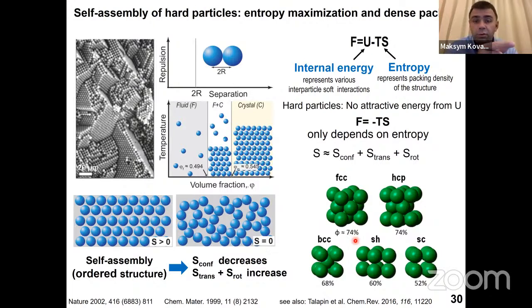They will undergo self-assembly into ordered states because at the late stage of drying, they maximize the free volume entropy, essentially. And even though they sacrifice the configurational entropy, you still get overall small entropy increase through the conversion into the ordered state at a very late stage of drying. And then the solvent evaporates fully, and then you are locked into a superlattice. And for spheres, you will end up with the structure, which is one of the densest sphere packing, which is face-centered cubic or hexagonal close packing.